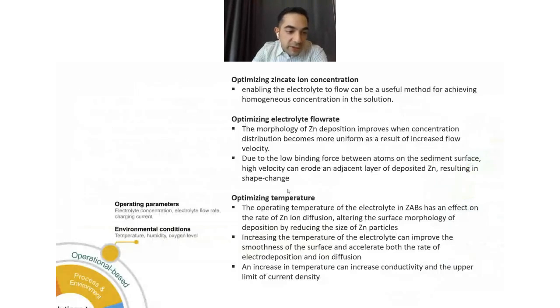And the third main category is the operational based strategies, in which the process operation and process factors are optimized in order to mitigate the anode related issues. Like zincate ion concentration, which affects the morphology of zinc, and also optimizing the velocity of the circulating fluid, and also optimizing the operating temperature. It effectively changes the rate of zinc ion diffusion, and alters the surface morphology of deposition by reducing the size of zinc particles.